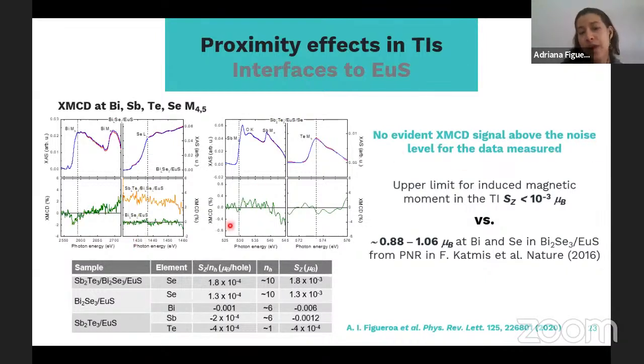But even so, we applied the magneto-optical sum rules to extract the magnetic moments for these atoms to establish an upper limit for the induced magnetic moment in these TIs, and we find that it is below 10^-3 Bohr magneton, which is in strong contrast to what is reported for these layers, for example, for bismuth selenide interfaced with europium sulfide, where it has been reported by polarized neutron reflectivity that they observed even 1 Bohr magneton at the bismuth and selenium atoms of these interfaces, which is really surprising.